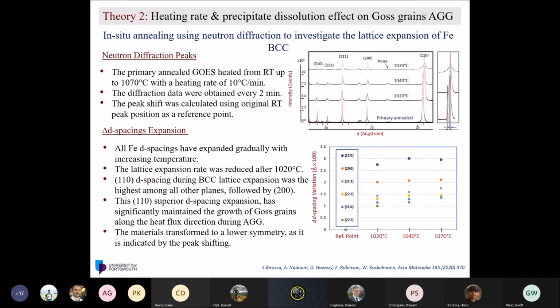So what we did, we applied for ISIS's neutron diffraction facility in Oxford. After so many rejections, we got some beam time. So what I'm showing here is what we did in situ neutron heat treatment. We take a primary annealed sample and heat treat it in situ using neutron diffraction from room temperature to 1070 with a specified heating rate.